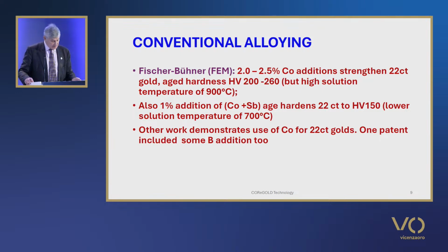There is also a patent by Taylor, who patented a 0.4% cobalt containing 22 karat gold, silver, copper alloy, but with a small addition of boron included. And this attains a hardness of 134 after 60% cold work. It is not clear what improvement in properties has been achieved over normal 22 karat gold compositions.